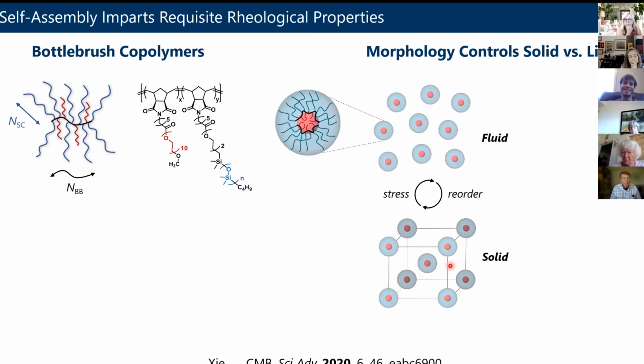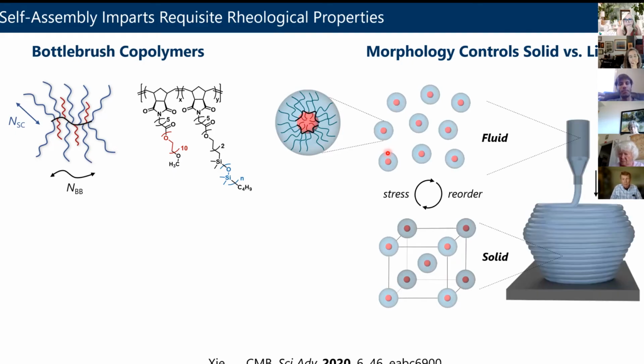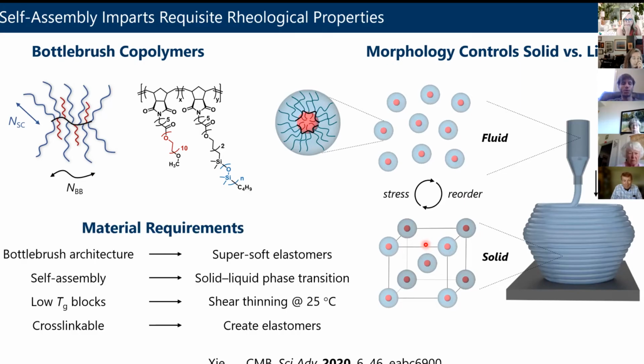But when you squeeze this thing out of a syringe, it becomes a fluid because the micelles lose their ordering. So they start sliding past each other. And we found that this is really fast going between these two states. When they lose their order, they flow like a liquid. But when you stop squeezing, they really, really quickly snap back into this BCC structure, which is solid. So to kind of summarize what we're doing here, we're using the bottlebrush architecture to create super soft elastomers. We're leveraging this type of self-assembly with two side chains now to give us this solid-liquid phase transition, which is how we're going to 3D print.